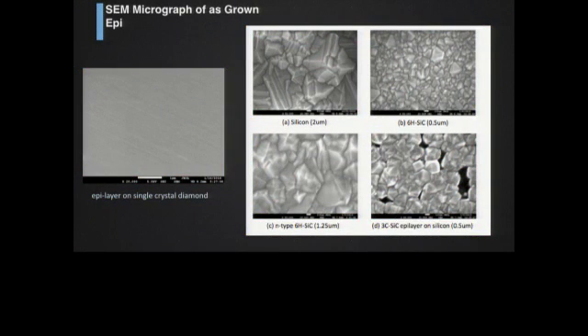This is an example of what the surface looks like after growth on single crystal diamond. This is the surface after we've grown on silicon, 6H silicon carbide, N-type 6H silicon carbide, 3C type silicon carbide, and this is various stages during the growth. This one being more advanced, these two being more advanced, and this one was stopped deliberately so we could get some idea of how the nucleation takes place and how the epitaxial film actually coalesces as a result of the growth process.